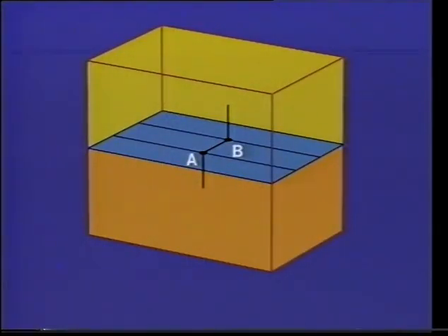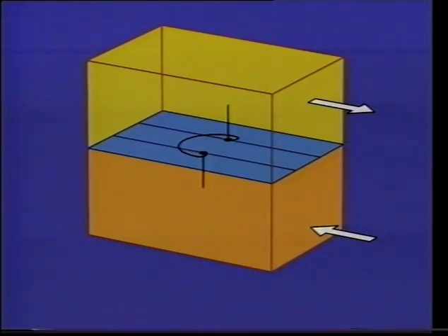We start by considering a dislocation having a short length lying in the shaded plane, pinned at the points A and B. It may be pinned at these points by intersecting dislocations. If we apply a shear stress to this dislocation, it can bow between the two pinned points until it has bent around sufficiently to send two new dislocations gliding away from itself in opposite directions. The whole process is able to repeat itself indefinitely, and so we have a source of dislocations.